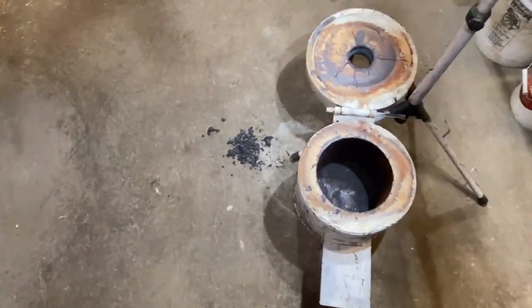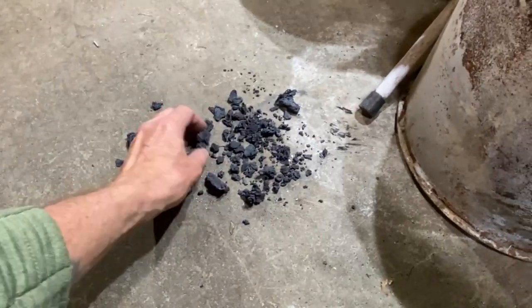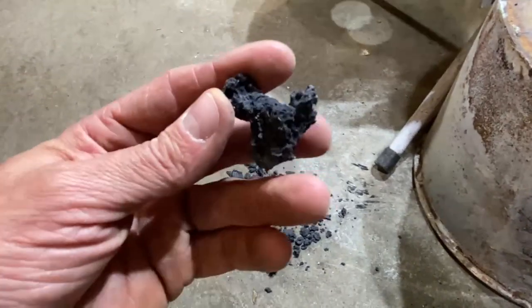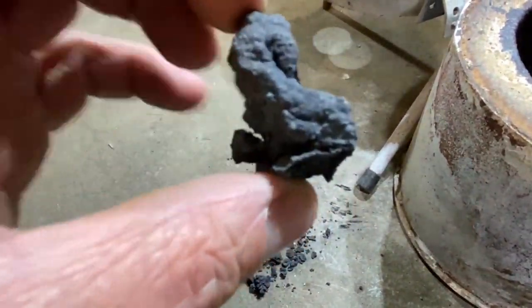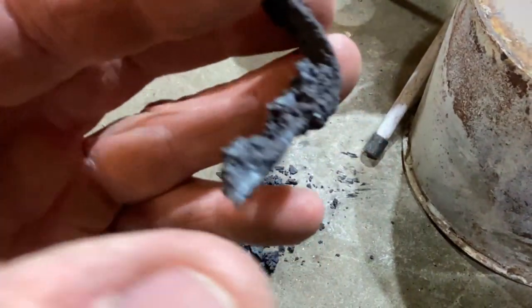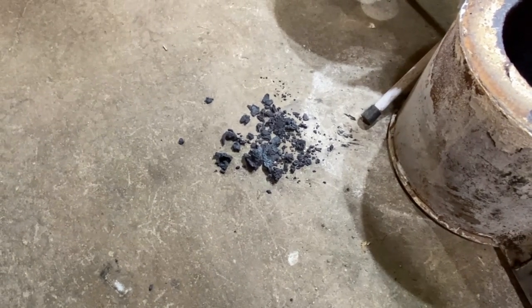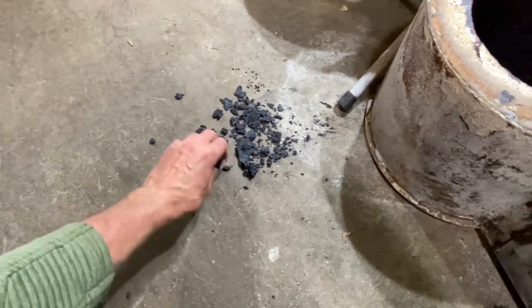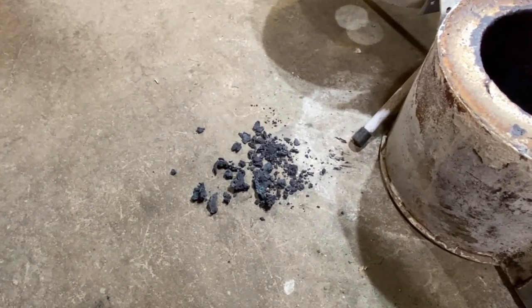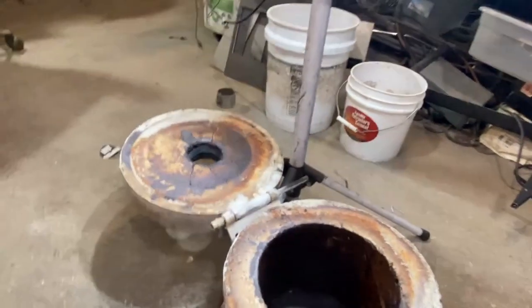Here is the stainless steel artifact — it completely sugared into chromium oxide. If you've ever welded stainless steel you're familiar with this material. There's just a small piece remaining buried in the sugaring. This piece of metal essentially proved the furnace temperature through an actual melting cone-type scenario, similar to furnace cones used in ceramics.